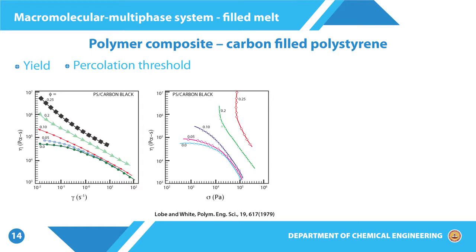So, the effect of shearing in carbon black dispersion is very similar at these strain rates, but at low strain rates we have a very different effect. The clusters that are available at 0.05 and 0.1 are not affected as significantly as the clusters at 0.25, and this is what is seen here also.